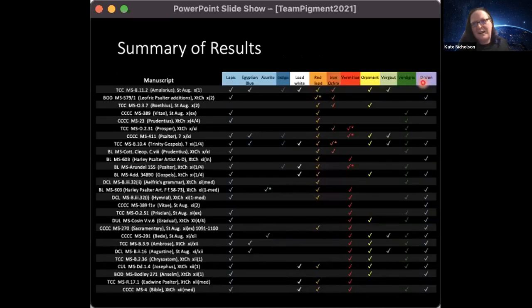But what we can do is look and see what trends are happening. Is it just a one-off? Is it random? And it appears to be quite random and sporadic to where the Egyptian blue turns up in the lapis. We also see that sea change from the use of red lead as our red of choice, and the takeover of vermilion. There's also quite an absence of orpiment in the early 10th century Canterbury manuscripts, and this coincides with the wars going on in Europe at that point in history, disrupting trade from Rome.